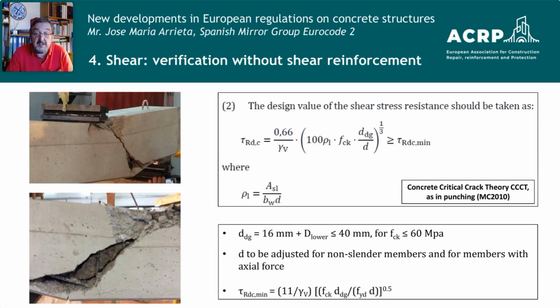You see the expression of the shear stress resistance. You can see this fraction, dg divided by, this is the size effect, and you can see a partial factor difference, gamma v, which really is gamma c, the partial factor of the concrete. What happens then? There has been a calibration of the shear formula, and it was possible to reduce the partial coefficient of the concrete for the shear and for the punching, and its new name is gamma v. With this value, the result is quite more accurate.